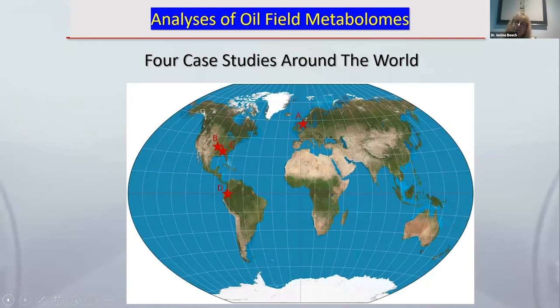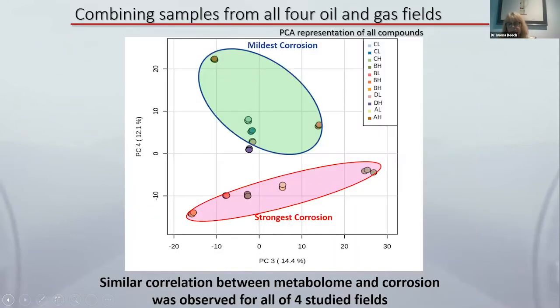So then when we compared all the data from all the cases around the world, we found that the systems that were corroding had very similar metabolomes, and the systems that were not corroding, or benign, or corroding as expected, all grouped in a certain way. So basically, it was the environment and perhaps the material, because obviously there's a certain cast iron that they're using for the production of the pipelines, that determined how the systems behaved irrespective of the geographic location.